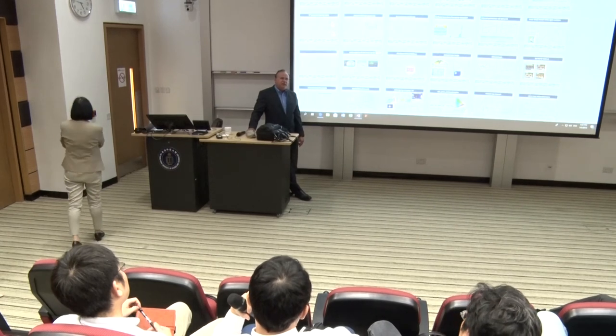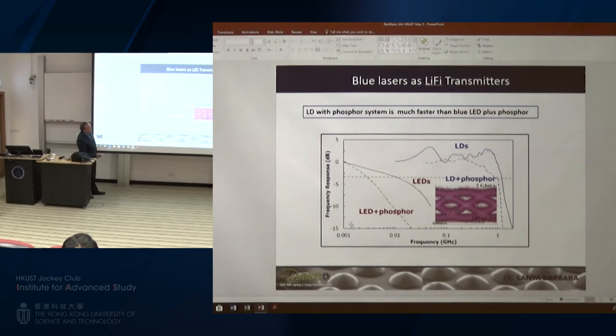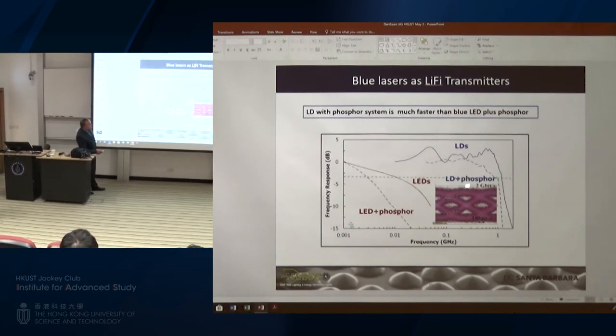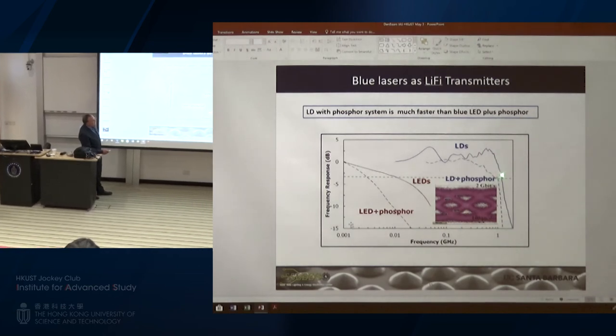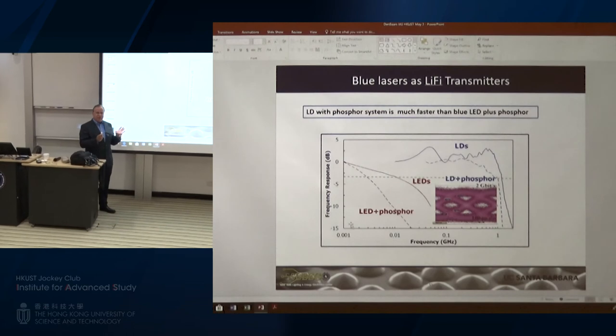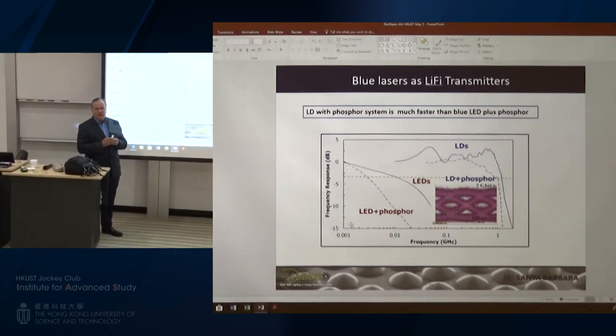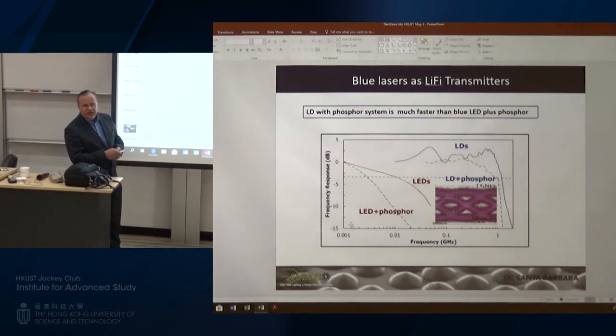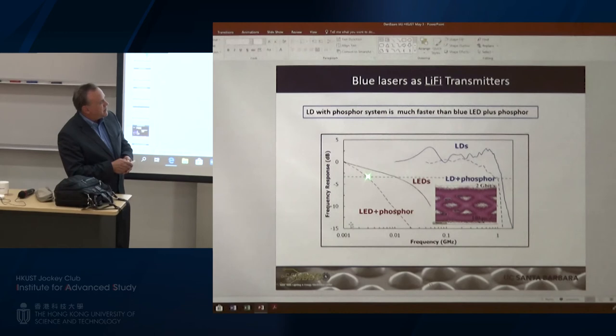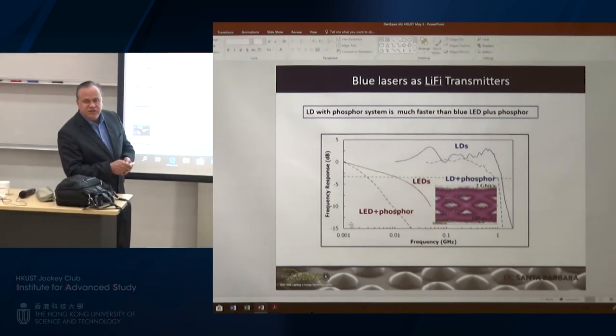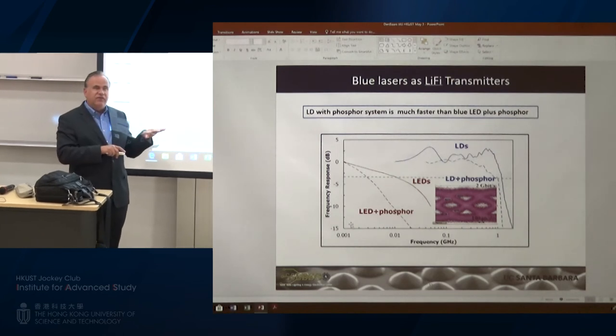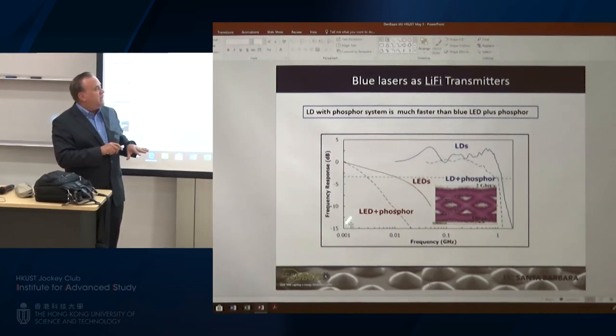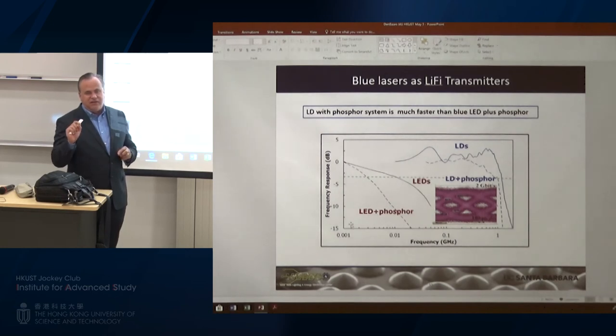That's a really good question. I think there is still a deficit. You see it here, but since you're at higher speed, the laser light, because it's a little bit more spectrally pure, is easier for the photodetector to lock in on. The blue was pretty broadband, 450, and there's some spectral overlap in the spectrum of the blue with the phosphor emission. The phosphor has an extremely slow decay time, on the order of hundreds of nanoseconds. The LED decay time is on the order of 10 nanoseconds. The laser decay time is much, much faster, on the order of picoseconds. That's the main reason. The laser has stimulated emission, a stimulated lifetime, versus spontaneous.